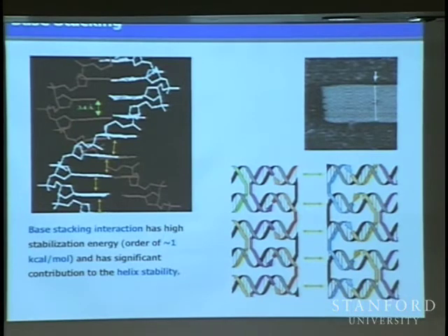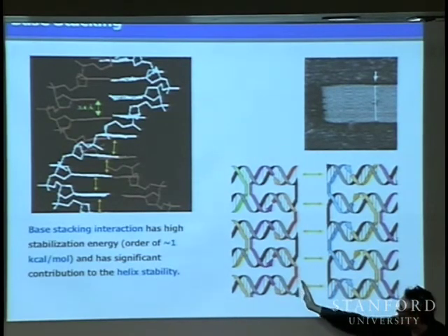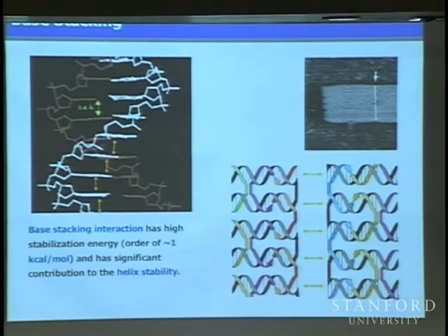Anyway, let's entertain the possibility. There's one point of view that says what makes the binding strength of the interaction of the 2 strands coming together, not the specificity, is this lateral interaction between this base pair and this base pair. Depending upon how you calculate it, based on different experiments, it could be 80 to more than 100% of the energy of the strands coming together. So the bases confer specificity and say which strand gets to stick to whom, but what's providing the strength is this stacking interaction. So if you have the edge of a DNA origami and the edge of another DNA origami, there's the end of one cylinder here, the end of another cylinder here, and the ends of the cylinders stick together.